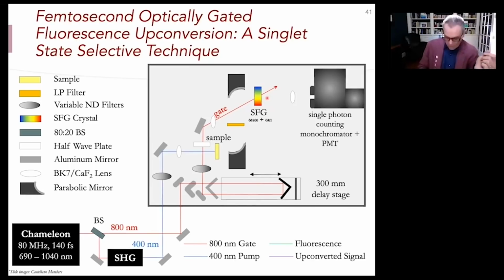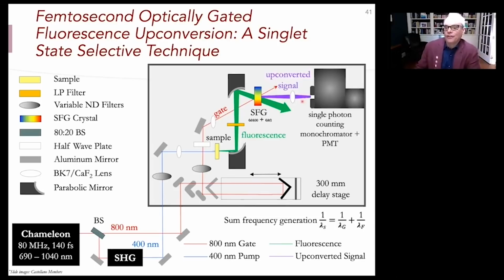But then we come in with the same pulse, split it into a 400 nanometer beam because it goes through a second harmonic generator. And then that hits the sample that's going to fluoresce. The fluorescence gets collected in a parabolic mirror collection system and then focused into the sum frequency generation crystal. Where they spatially and temporally overlap, you get a time-dependent upconversion signal. The time dependence is based on the intensities of the two signals. The gate is always constant intensity. The fluorescence is a time-dependent signal. So this generates an upconverted signal that's proportional to the fluorescence decay of the sample itself on ultra-fast timescales.